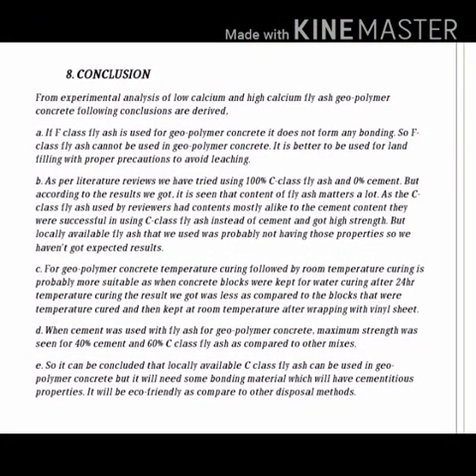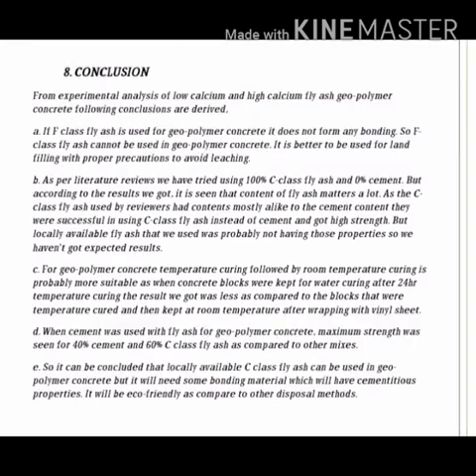In conclusion, F-class fly ash does not give proper bonding for 100 percent replacement. Similarly, when C-class fly ash is used alone, it gives very low strength and uneven finishing. For concrete with 60 percent fly ash and 40 percent cement, we obtained maximum strength.